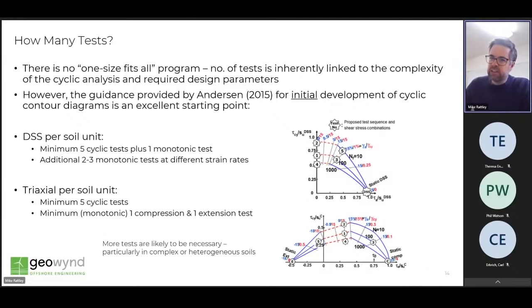Alternatively, you'd need both a compression and extension test for triaxial conditions to map the full interaction diagram of cyclic response. I'd also recommend a further additional 2 to 3 monotonic tests performed at different strain rates to assess the rate dependency of the soil response, as that's an incredibly important aspect of cyclic response and interpretation of the test data. Those rate dependency tests are most efficiently performed in the DSS apparatus. But essentially, whether you're looking at DSS or triaxial tests or both, will depend on the requirements of the planned cyclic analysis. So those really need to be known ahead of specification of the cyclic program to avoid either not getting the right data or generating data wastage in the program.